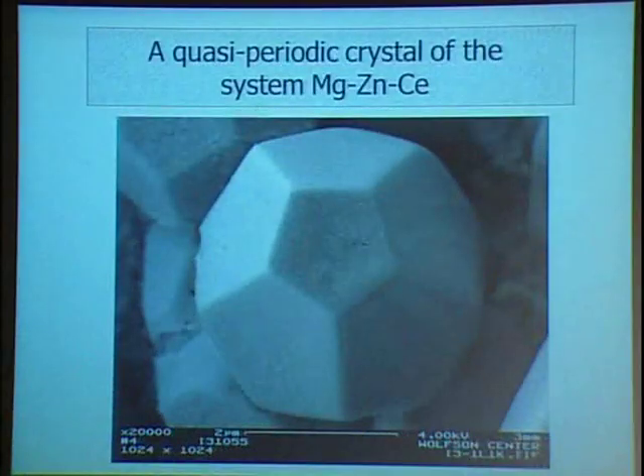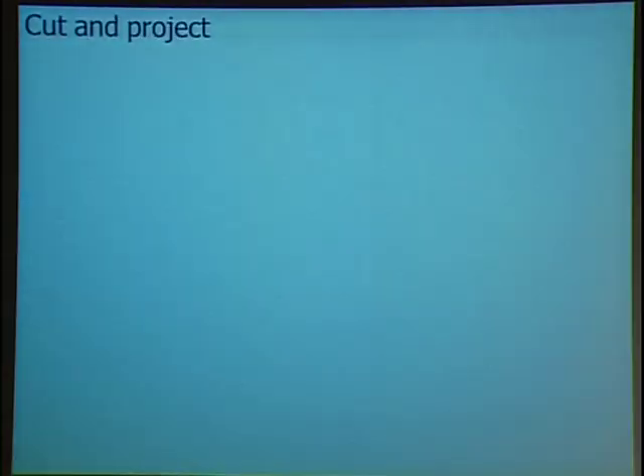Three dimensions. Quasi-periodicity in three dimensions. Here's the crystal taken by Ina Popov from my laboratory years ago. So this is a quasi-periodic crystal, and the composition is magnesium, zinc, cerium. And you can clearly see the beautiful five-fold facet. So this is in three dimensions. So we have one dimension quasi-periodicity, two dimensions, three dimensions quasi-periodicity.